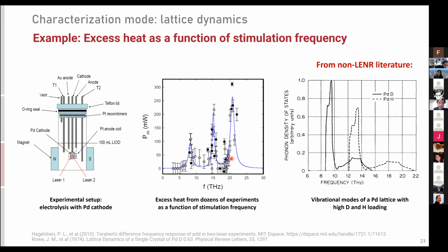Okay, so then I think another interesting result that gives us some potential information about what might be going on is this series of experiments. I think this is particularly interesting because it's actually a series of dozens of experiments that were done in a similar setup again, with a little piece of palladium in a heavy water-based electrolyte. But this time, 2 lasers were pointed at the sample, and the hope of pointing the lasers was to stimulate the lattice, to cause these kind of waves, vibrations that you saw earlier in the little videos.